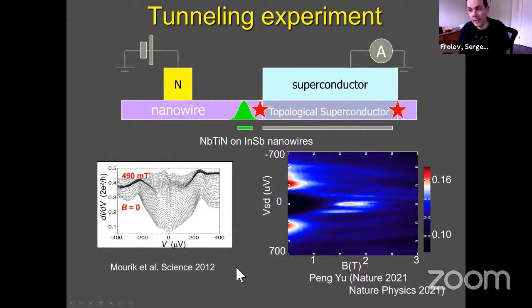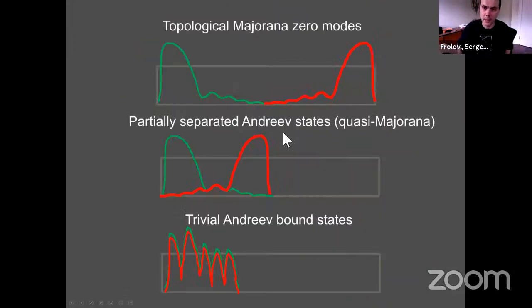Now, this is from Pittsburgh. This is also our data from 2012, when I was a postdoc in Delft. This is from Pittsburgh, where now it's a color scale, so I can introduce it to you. It's conductance, so dI/dV, in units of 2e squared over h, a quantum of conductance. Dark blue means low conductance, and red means high conductance. So this is a very narrow peak. It appears at finite field and it stays there. If I give you Zeeman energy, then if there were a state that had spin, it would start here at the bottom and cross all the way out to this window of energy, because the g factor of this material, indium antimonide, is 50. So you have a large Zeeman energy.